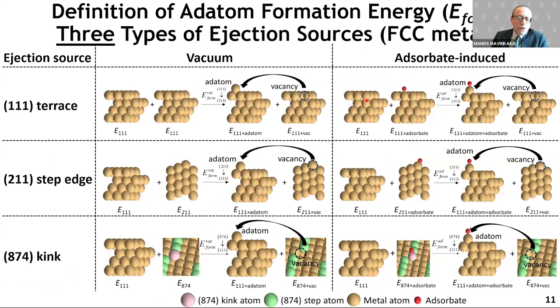So the framework that we then established, very simple, to evaluate the energetics of adatom formation. Here is the ejection source. Depending on the geometry from where you eject an atom, a metal atom from, this is the hexagonally packed 111 facet for FCC metals. This is a step edge, undercoordinated. Here you see the step edge cross-section view. This is a kink site, most undercoordinated. The energetics will be different.